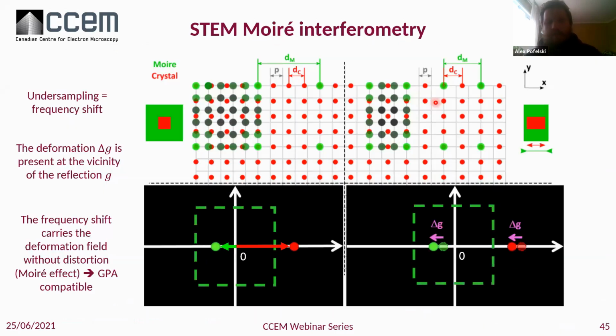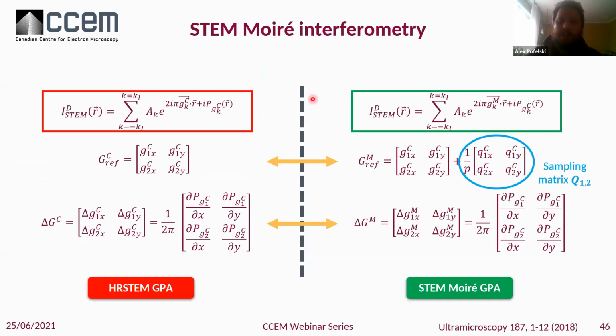Because then, regarding the strain, the deformation, this Fourier space shift that is caused by undersampling explains absolutely everything that you see in this geometrical intuitive approach that we try. So the delta G that is representing the strain is present in the vicinity of the reflection. Whenever you undergo a shift, the shift is carrying the delta G without any distortion. And this is the key element here, which means that the delta G that is either taken from the red spot or the green spot, the shifted one, they are identical and they are therefore GPA compatible. So you can use directly the GPA method.